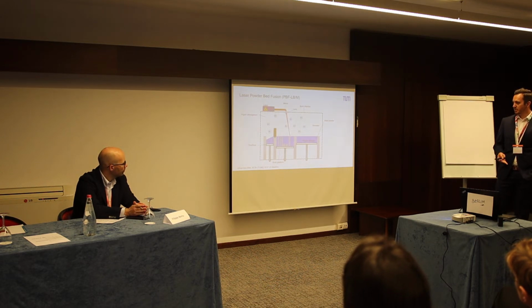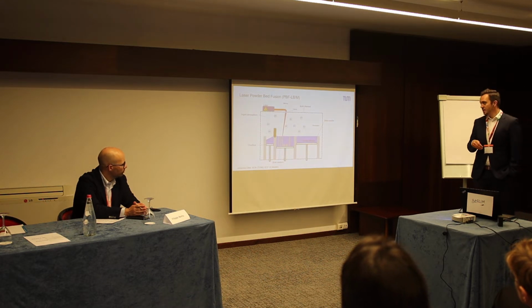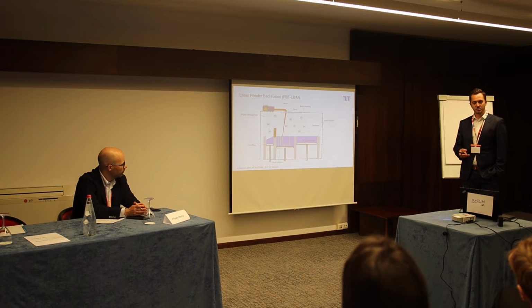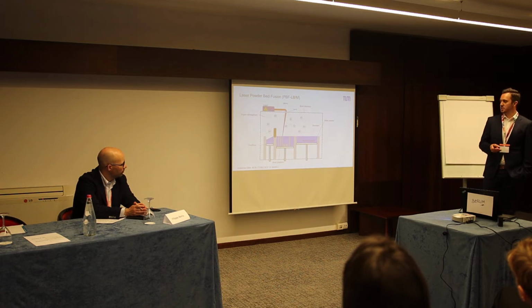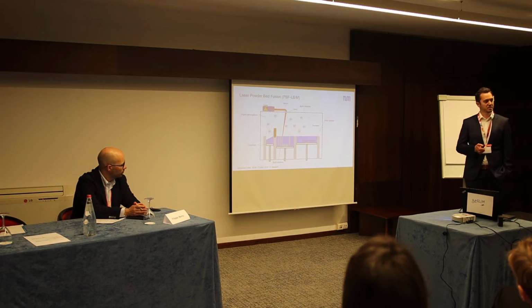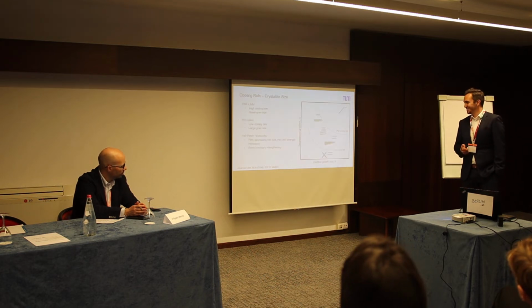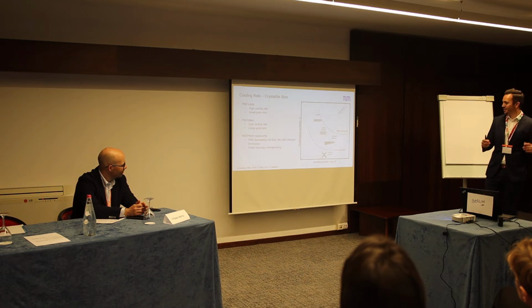So what's important here is that we have a high energy density, or a high energy input, in a very small area, meaning that we have a fast liquefaction and a small solidification, or very high cooling rate, I would say, of up to 40 Kelvin per microsecond, depending on the literature. Great differences in between that.